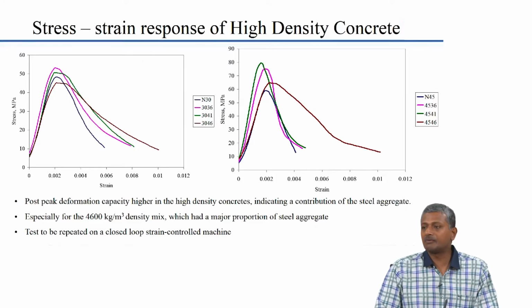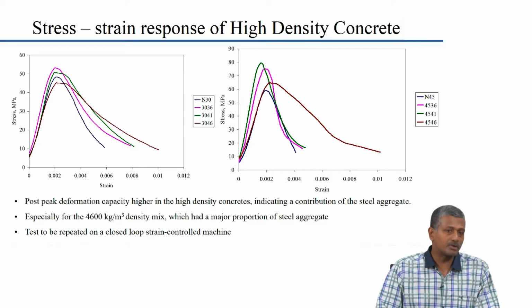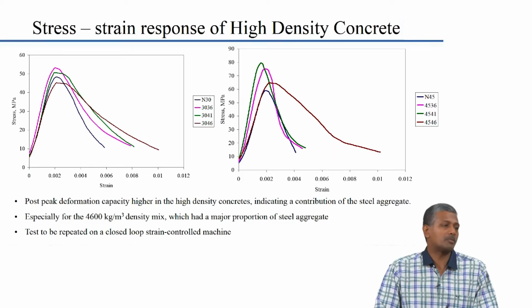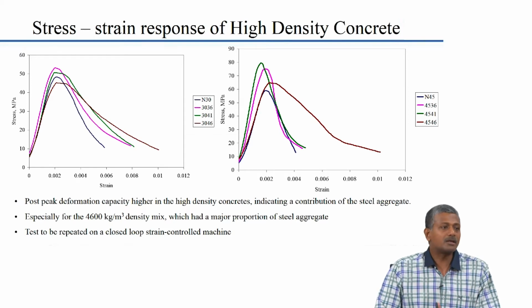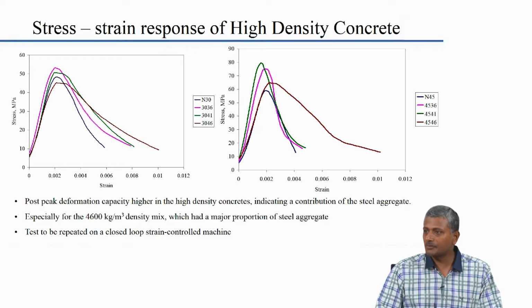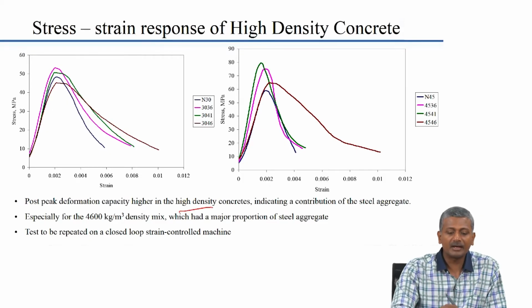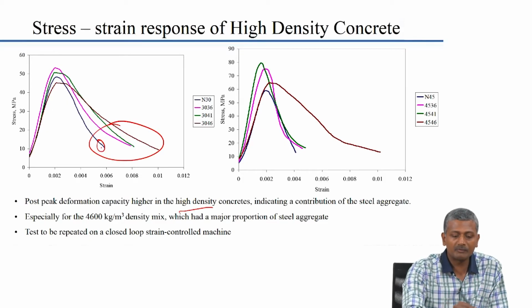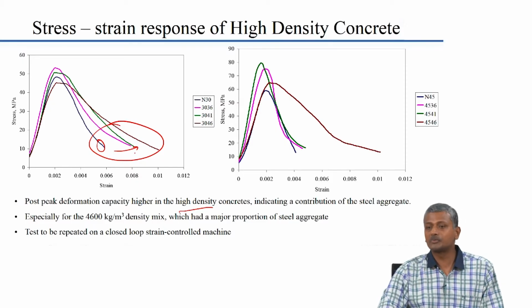So, here this was a project that we were actually doing for Indira Gandhi Center for Atomic Research, where we had to look at the structural characteristics of high density concrete, because apart from the radiation shielding characteristics, we also had to get some estimate of what the engineering properties of these high density concretes were. So, we attempted to study this high density concrete using a compressive stress strain relationship like what I had showed you earlier. We tried to measure the compressive stress strain relationship by using cylindrical specimens and observing the deformation when the load was applied, and this was exactly in the same sort of a way that I had demonstrated earlier. So, here the post peak deformation capacity is higher in the high density concrete. So, you can see that compared to normal weight concrete which is here, the high density concrete seem to have a higher post peak deformation capacity.